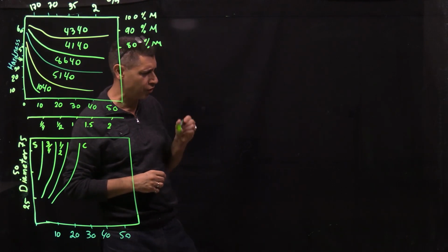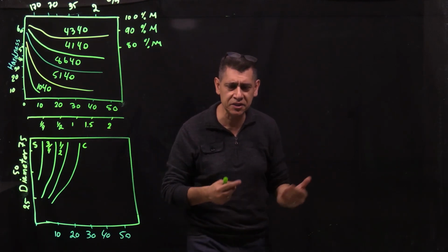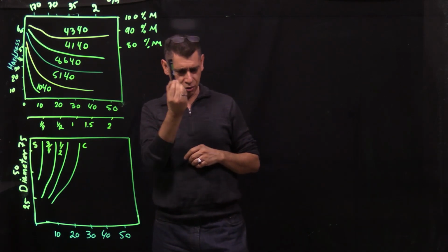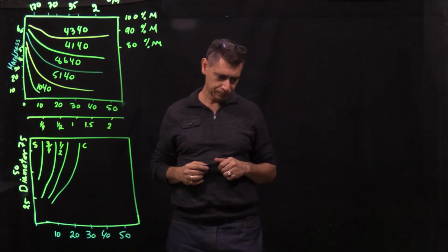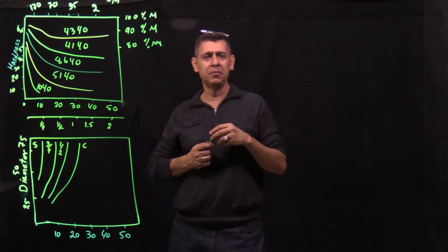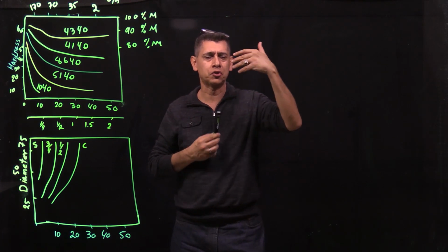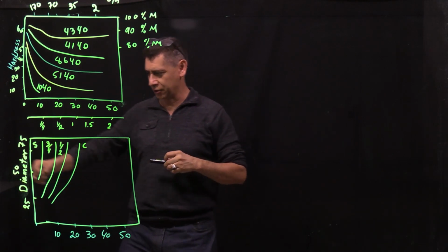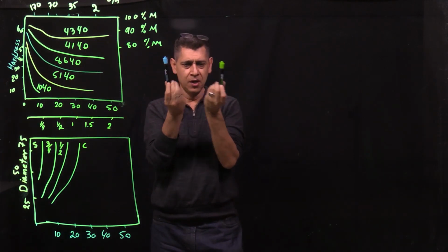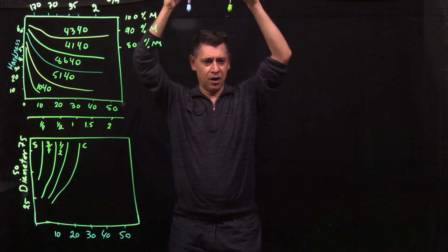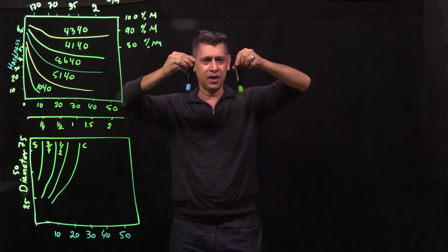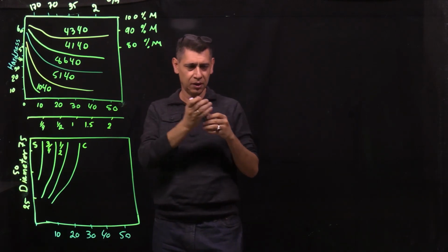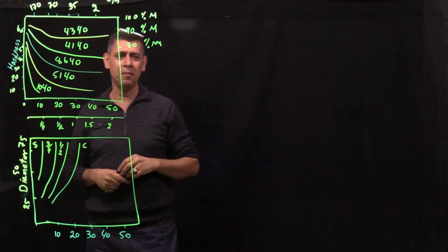The definition of hardenability is how easily this material can be transformed to martensite. How easily means how slowly you can cool it and still get martensite. A really practical way of doing it: I have these two alloys, I have the same size, and I cool them down with the same rate, and I will see which one gets more martensite. The one that gets more martensite is more hardenable. But the Jominy test made it easier.